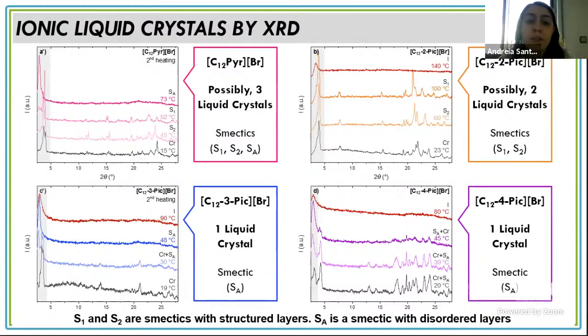In order to characterize which mesophase is present in each material, X-ray diffraction studies were performed. For C12 pyridinium bromide, possibly 3 different liquid crystals were detected, being S1 and S2 smectic with structured layers, as it is possible to detect a strong intense peak at small scattering angles and low intensity peaks at large scattering angles. It was also detected smectic A, which is smectic with disordered layers, as it was possible to observe only the intense peak at small scattering angles.